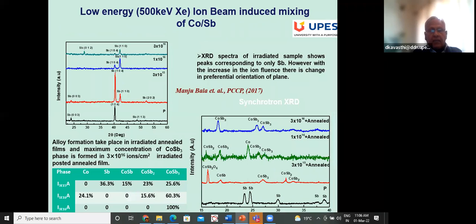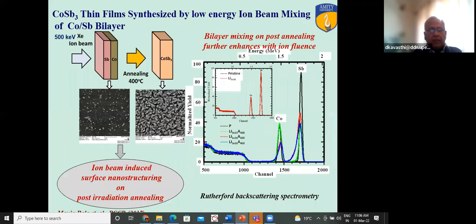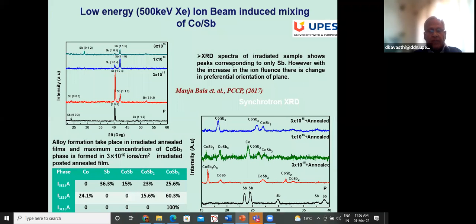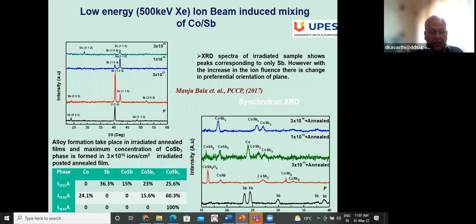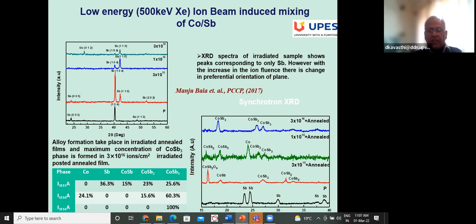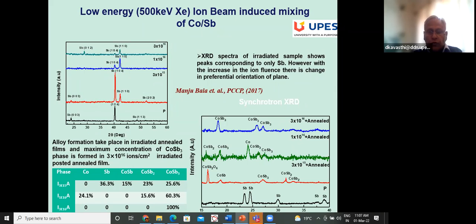In another experiment, the cobalt-antimony system is irradiated by low energy ions — 500 keV xenon ions. The table below shows that we are able to make 100% CoSb₃. If we irradiate with low energy ions and anneal further, we get 100% CoSb₃, which is of tremendous interest. This is proven with synchrotron XRD, confirming a complete CoSb₃ phase in a particular case.